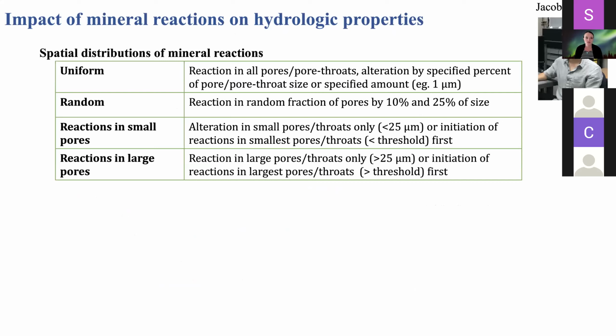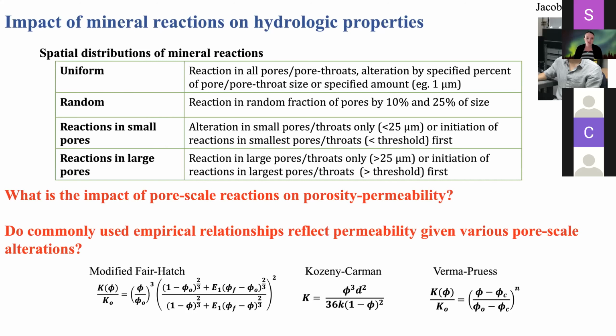What we are doing here is using our pore network model to try to understand the variation in permeability as the spatial distribution of mineral reactions changes. That goes from reactions being uniformly distributed on all surfaces, to randomly distributed, only impacting a fraction of the pores and pore throats, and then occurring preferentially in or being inhibited in small and large pores and pore throats. The work I'm going to share with you today was done by my undergraduate researcher, Jacob Benzinger. And from our pore network model, we also wanted to know: do these empirical relationships accurately reflect the evolution of permeability given these variations at the pore scale?